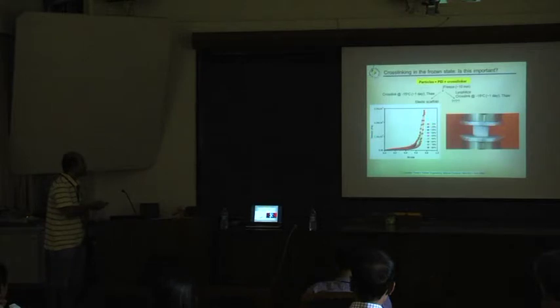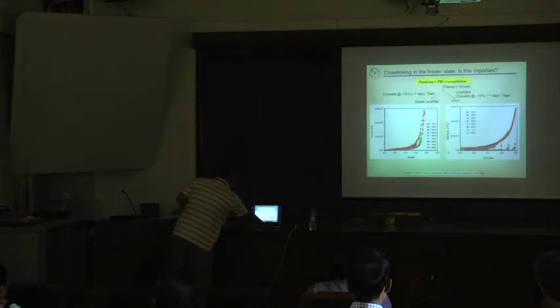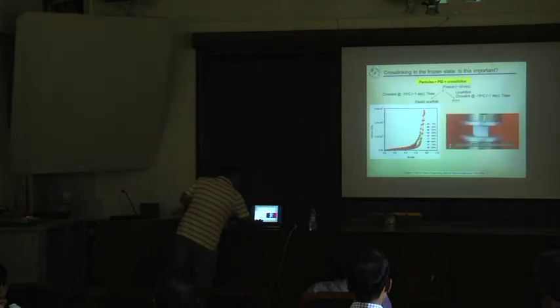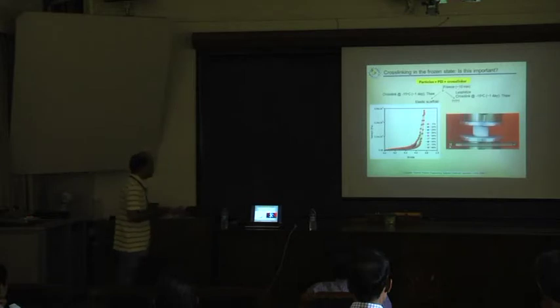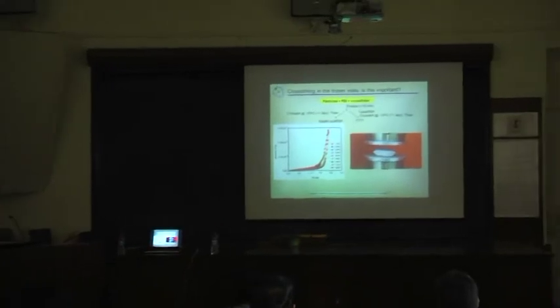So you can sort of compress it to about 90%, and it comes back to the original position. These materials, however, do something very different, and this is the work of Karthika, who has a poster on this. And what you see is, unlike the previous materials, as you start compressing this, done without the water in there, you can start seeing cracks develop, which doesn't show up very nicely in here. Essentially, this stuff just flattens out, right?